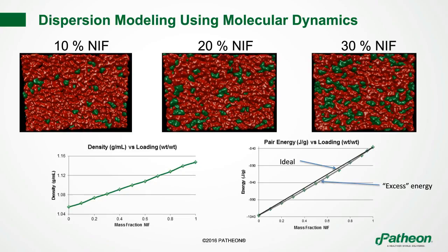This is exactly what we looked at from an experimental perspective. You've got excess energy. It's endothermic in this sense. So you're seeing here, essentially, the pair energy is modeling the enthalpy of mixing. That's directly from the simulation. You see this very nice plot here that I'll actually blow up on the next slide that shows that we're modeling this non-ideal behavior that we measured experimentally for the exact same system, nifedipine and PVP.